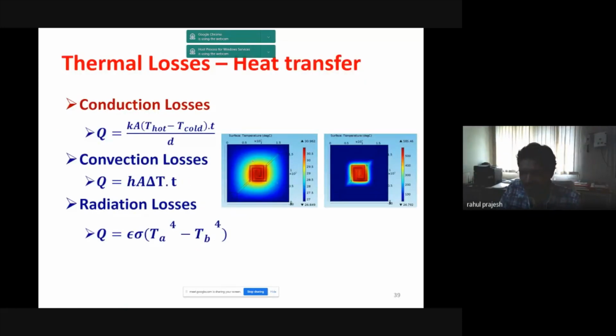Now, if you see the difference, this is a simulation. Two cases are taken. This is the first case where you have not removed the material from the back, and if you see, the temperature is spread out across the chip, and also the maximum temperature is only going up to 31 degrees centigrade approximately. And if you see the other case where you have removed the silicon from the back, now you see over here the temperature is going up to 585 degrees centigrade.